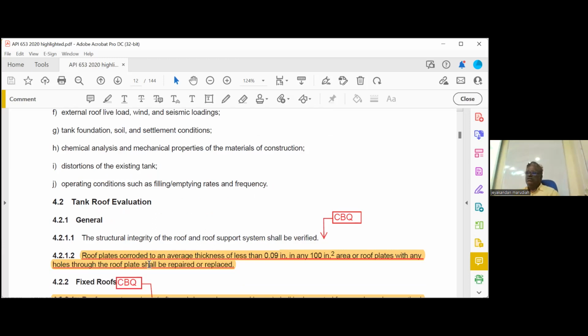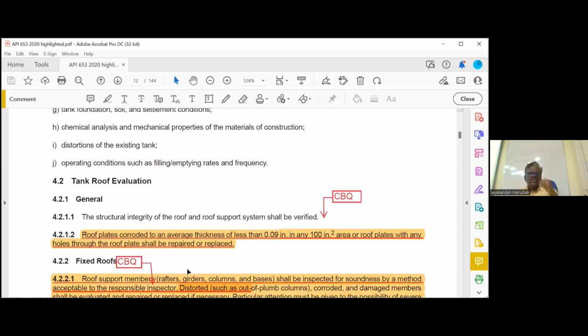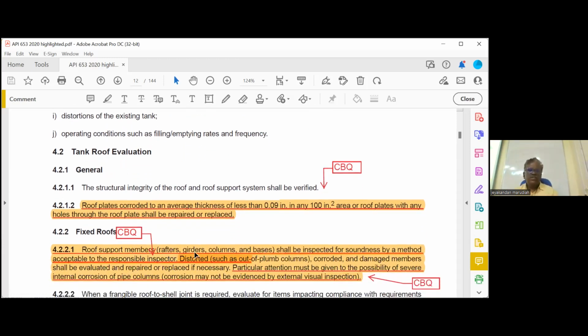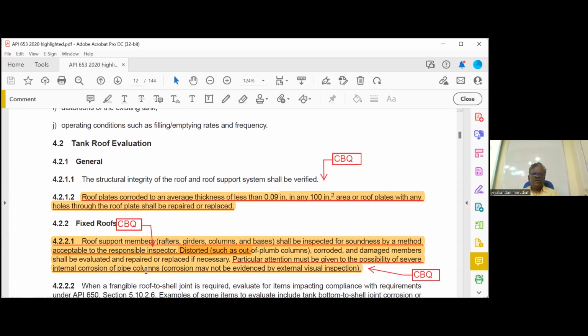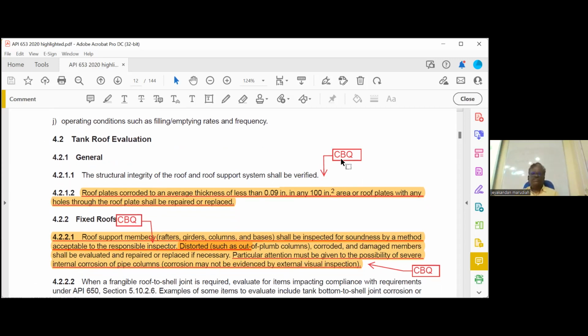Roof plates corroded to an average thickness less than 0.09 inch in any 100 square inch area, or roof plates with any holes through the roof plate, shall be repaired or replaced. Very, very important closed book question. Then the next one, fixed roofs. Roof support members, rafters, girders, columns, and the bases shall be inspected for soundness by a method acceptable to the responsible inspector. Who will inspect? Responsible inspector. That line is important. Next line, particular attention must be given to the possibility of severe internal corrosion of pipe columns. Corrosion may not be evidenced by the external visual inspection. That is also important. For columns, we have to check whether they are corroding inside by doing UT thickness readings.